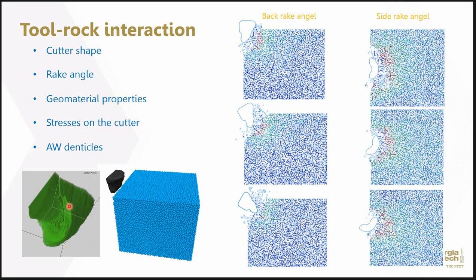So we do see that the curved surface helps to minimize the damage during cutting, as well as leave a relatively larger scratching mark than the width of the denticle itself. And also the cutting angle of most of the denticles is around 15 to 45 degrees, so close to 30 degrees of optimum rake angle there.